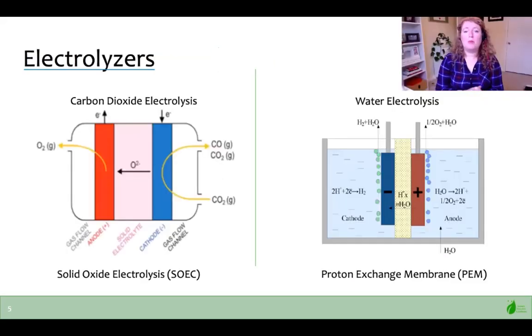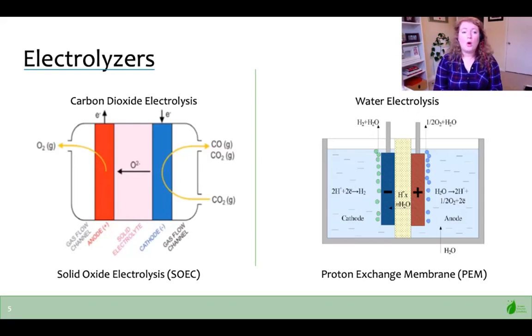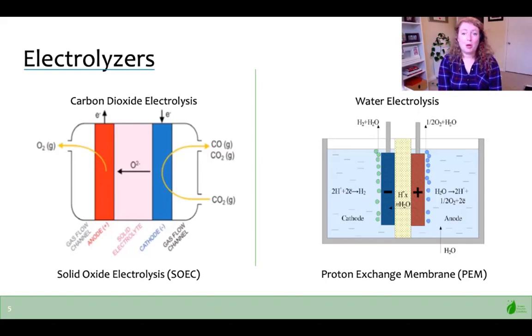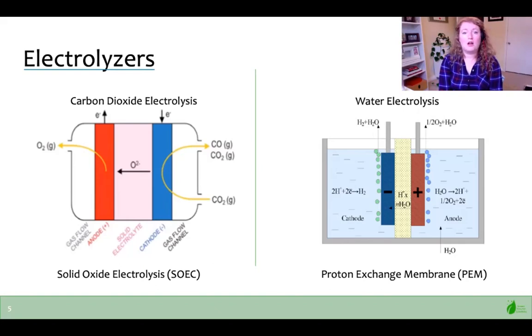We have two electrolyzers in our proposed multi-step design for methanol synthesis from syngas. CO2 electrolysis is an emerging method to produce carbon monoxide without the use of steam methane reforming. Water electrolysis for the production of hydrogen is a well-established technology and is currently employed in industrial settings. In solid oxide electrolysis, or SOEC, the electrolyte is a solid ceramic which can conduct oxygen oxide ions at high temperatures but remains impermeable to electrons and oxygen gas. This electrolyte facilitates the electrochemical reduction reaction at the cathode and the oxidation reaction at the anode to produce carbon monoxide and oxygen. CO2 electrolysis to CO is an emerging technology with minimal industrial application but is rapidly becoming commercially viable.